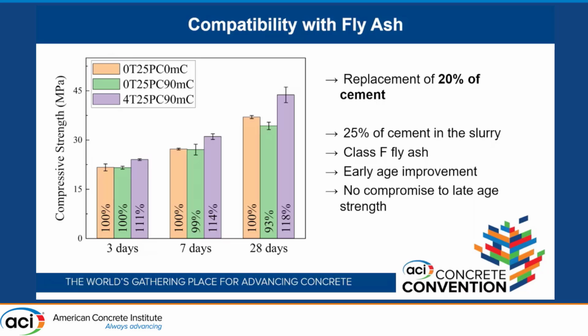mostly because once you have the CO2, you can have some problems with the pH, and maybe not trigger the pozzolanic reaction the way you would like to. But once you add the tannic acid, you can see that from 3 days, and it carries on all the way to 28 days, you get improvement to almost 20% at 28 days.